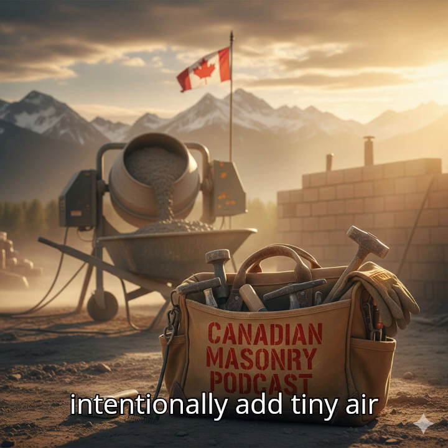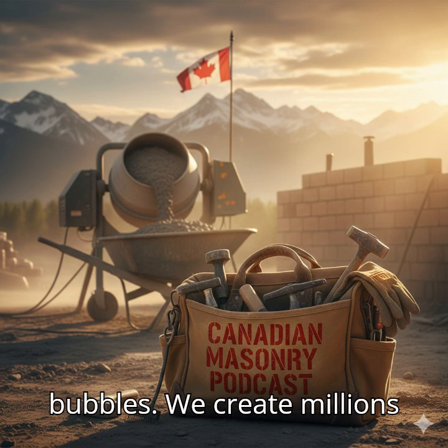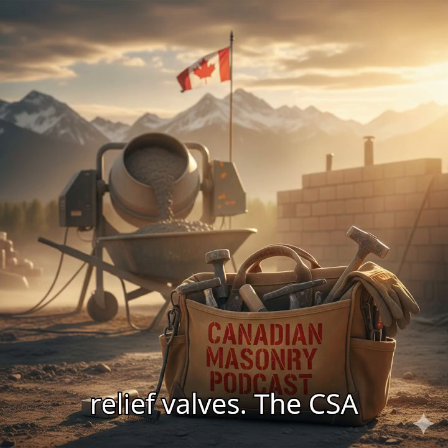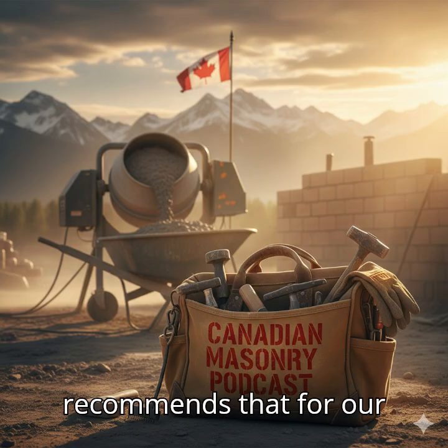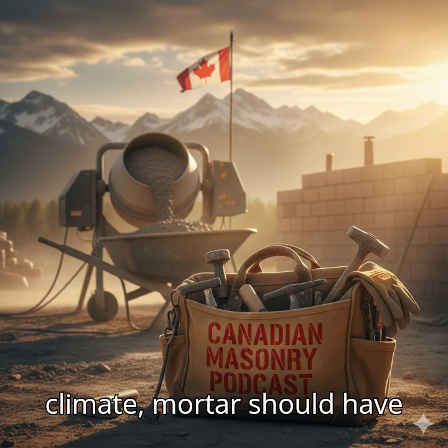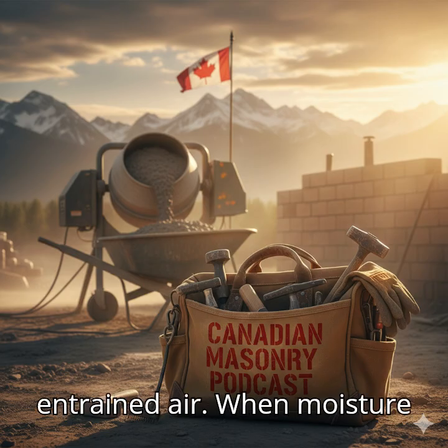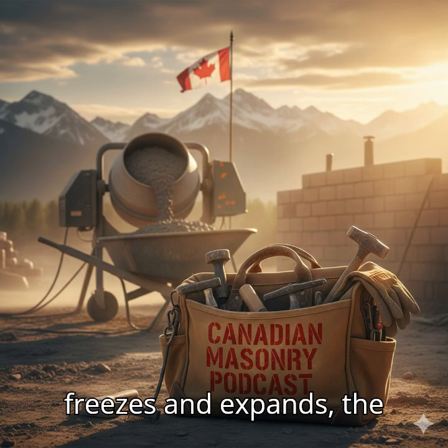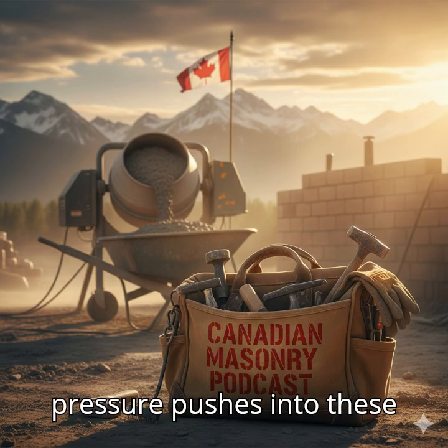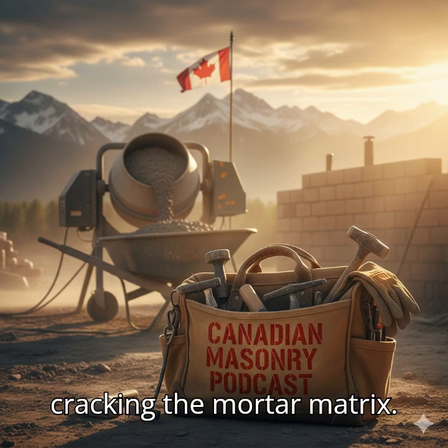So we intentionally add tiny air bubbles. We create millions of microscopic pressure relief valves. The CSA recommends that for our climate, mortar should have about 8 to 15% intentionally entrained air. When moisture freezes and expands, the pressure pushes into these tiny empty voids instead of cracking the mortar matrix.